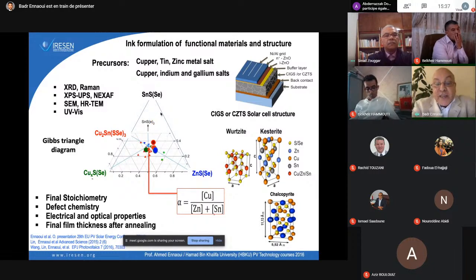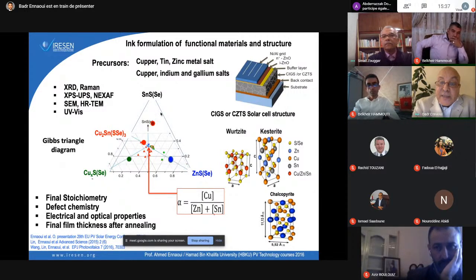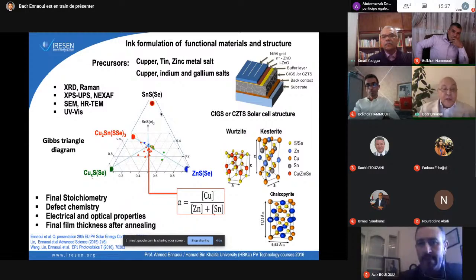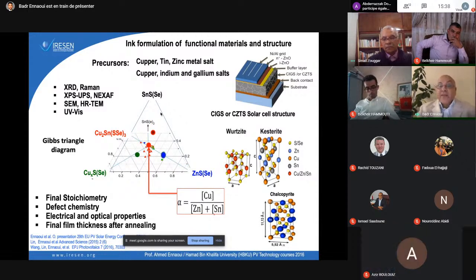as a parameter, and we see how to make engineering of our three binary compounds in order to prepare the ternary compound. It's a lot of work in the beginning, a systematic work where you have to find out the final stoichiometry, you have to study the defect chemistry, the electrical and optical properties in order to have a final thickness after annealing and to find the photoactive material and to make the device.